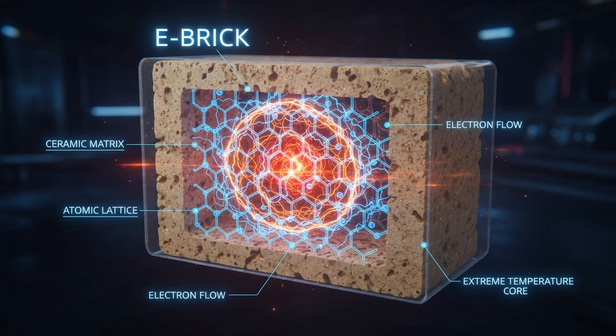So when you plug a Joule Hive into the grid, electricity flows directly through the stack of bricks. The bricks themselves become the heating element. Because they are made of refractory ceramic materials designed to withstand extreme environments, they can safely reach temperatures of 1800 degrees Celsius, or nearly 3300 degrees Fahrenheit. That is hotter than the melting point of steel and hot enough for virtually any industrial process.